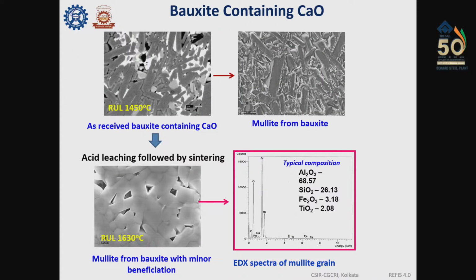So we have done some work on this. The first one is bauxite where CaO is there. First we straightaway tried to convert it to mullite. The low melting phase formation was restricted, but the mullite formed was elongated in shape. Then we took a separate approach where we leached the CaO with a minor acid, maybe an organic acid, and we got almost equiaxed mullite, where we could achieve RUL values of 1630 degrees centigrade. At the same time, the EDAX pattern of the mullite grains clearly shows that iron oxide and TiO2 are incorporated in the mullite grains, and thereby it reduces the low melting phase formation.